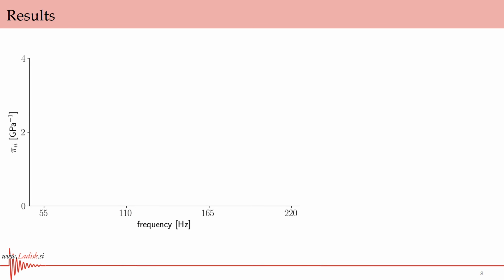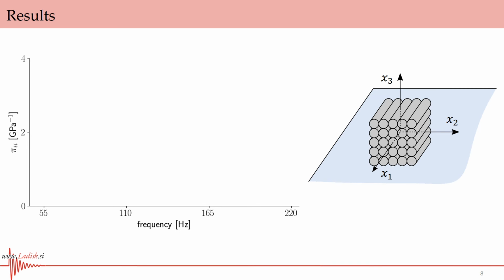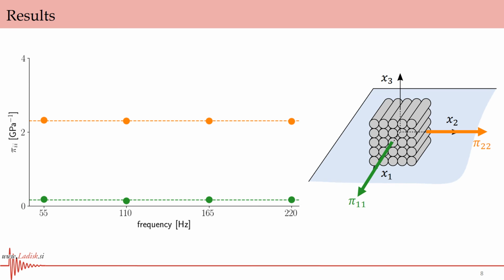To evaluate the applicability of the proposed method, piezoresistive coefficients in 55 to 220 Hz mechanical excitation frequency range were measured. The lowest piezoresistive coefficient was obtained in the material deposition direction, followed by direction transverse to material deposition direction in horizontal plane and in vertical plane. Obtained piezoresistive coefficients showed no frequency dependence, which is good information for development of dynamic sensors.